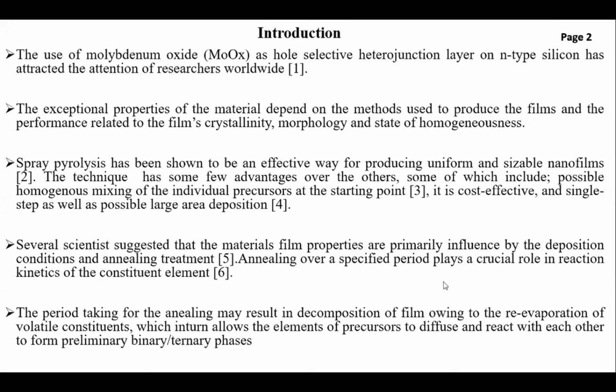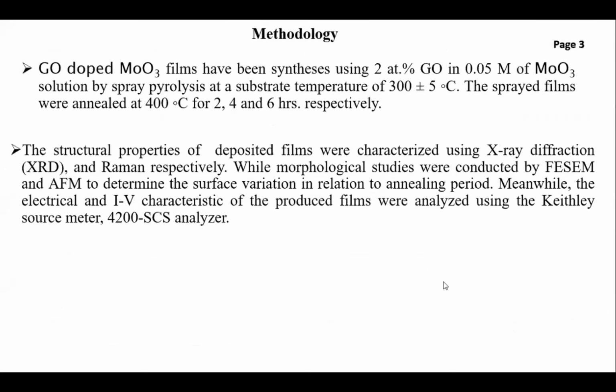As such, several scientists suggested that material film properties are primarily influenced by the deposition conditions, which include annealing as well as the specified period for annealing. The period taken for the annealing may affect the composition of the films owing to the evaporation of the volatile constituents, which in turn allows the elements of precursors to diffuse and react with each other to form binary or ternary phases. Now, methodology.